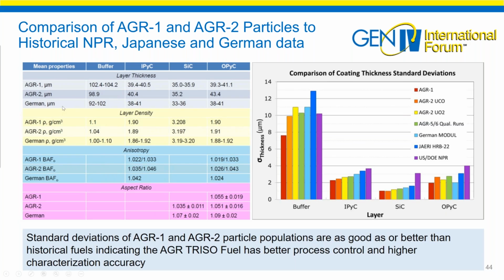You will see that there's a wide mean in here, so that if a fabricator is within these bounds, it is possible to, you could interpolate, but I wouldn't extrapolate. All right. If you have, for instance, too large of an OPyC layer, that acts to constrain the particle, and the IPyC there's compression, and then the inside, and they're holding the SiC layer together. So you'd have to be very careful.